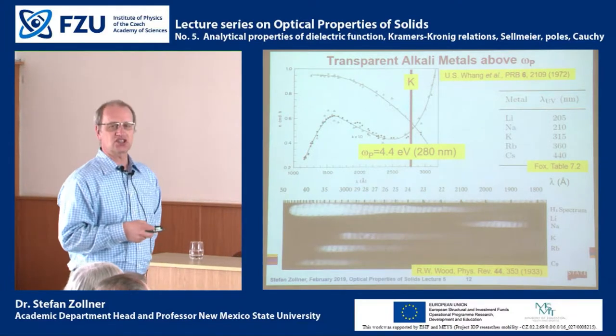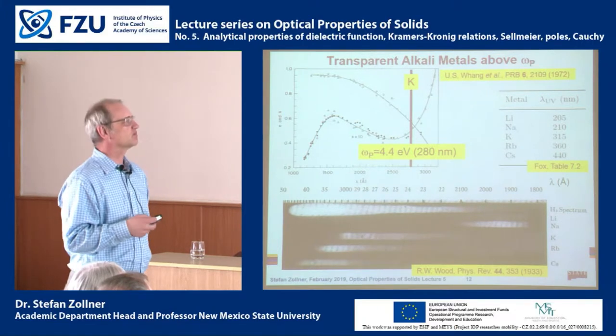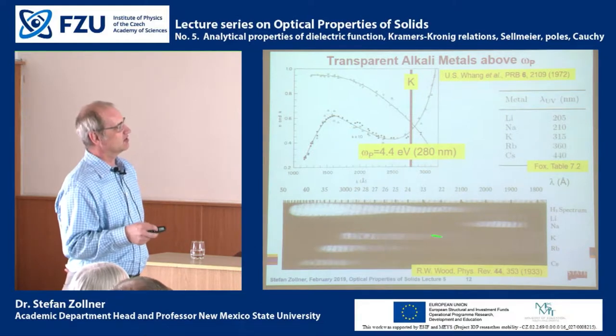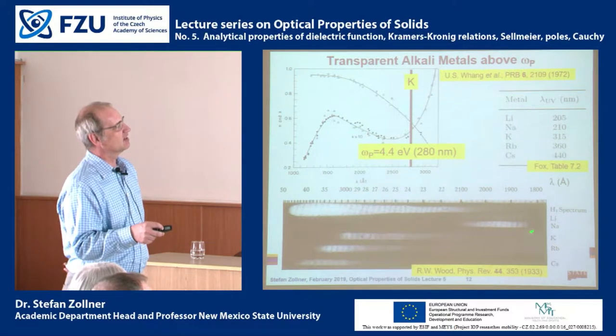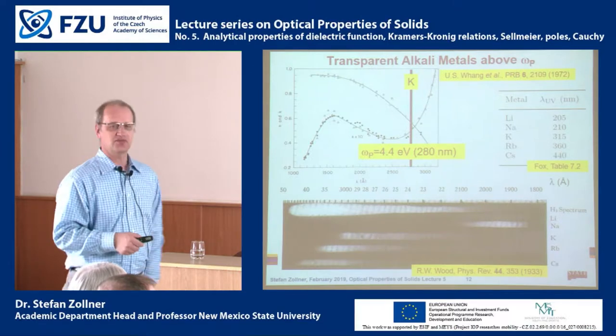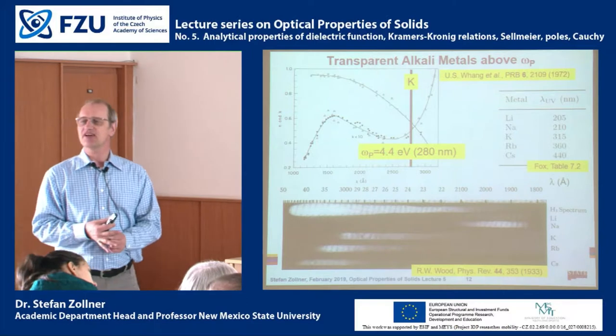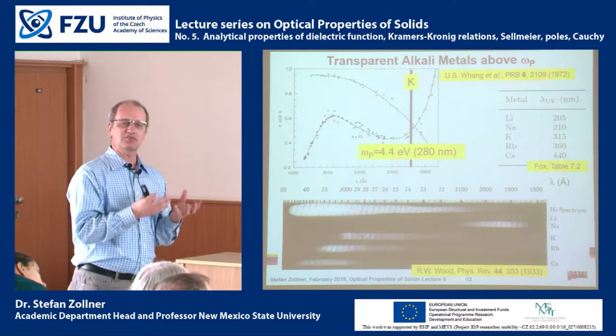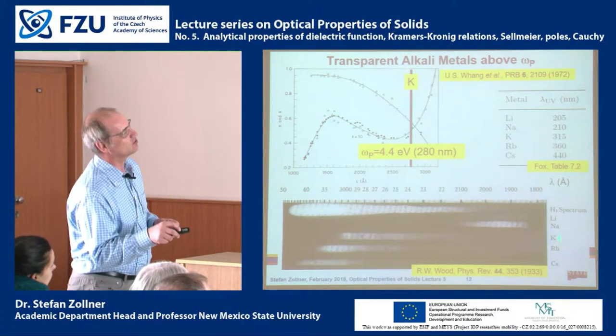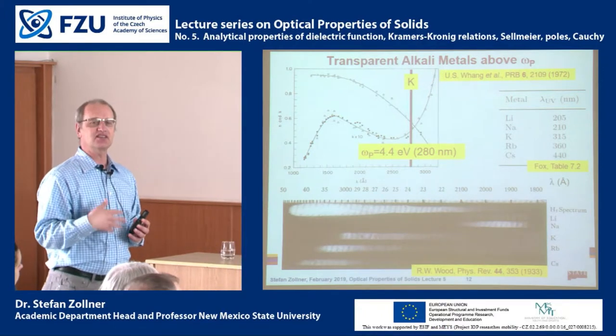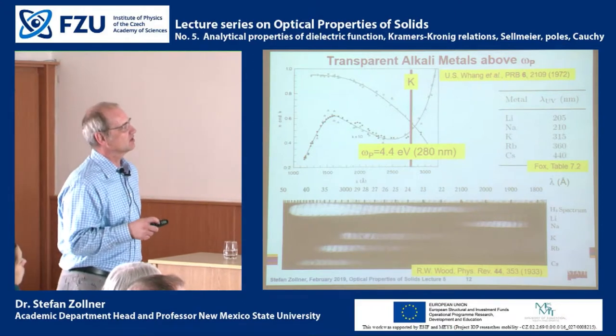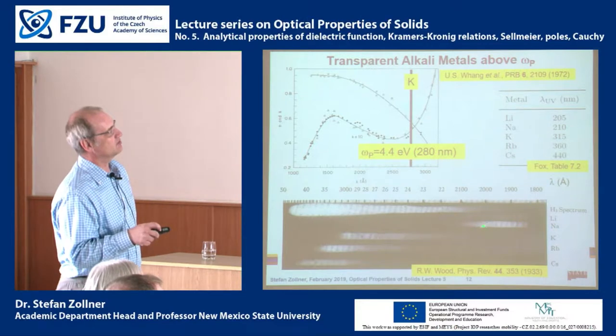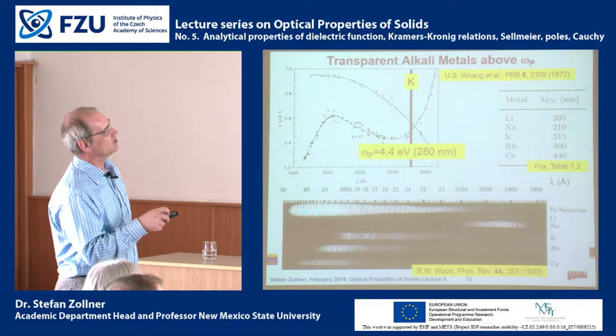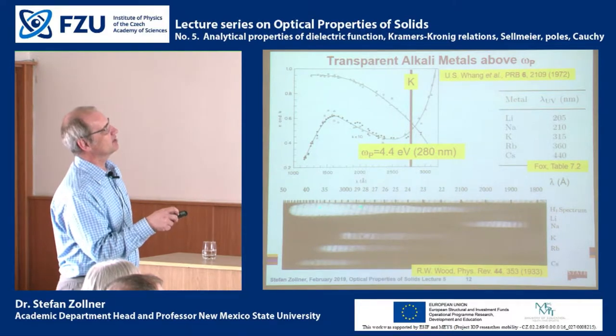Nevertheless, there are experiments which demonstrate that thin layers of alkali metals become transparent. And there is this paper here from 1933. What you see here is a photograph of the transmission of a thin layer of metal. They made this bulb and they evaporated some metal, very thin. You can imagine it's not so easy to measure alkali metals because they are very unstable. They immediately react with oxygen and water. Let's look at this curve here. This is sodium. The top line is the spectrum of the lamp, and the hydrogen lamp has most intensity at around 4,000 or 3,000 angstroms. That's the transmission spectrum without a sample.